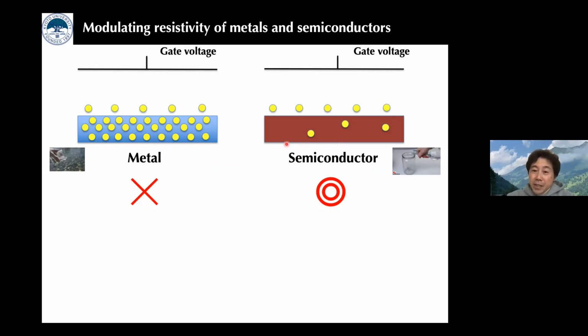However, we can fabricate transistors when we use semiconducting materials, because we can control the carrier density, and at the same time we can suppress the carrier density in it. In such a case, when we apply strong gate voltages yielding dense carrier accumulation in the system, we can largely control the conductivity of semiconductors by the gating, and this allows the large on-off ratio of the system.